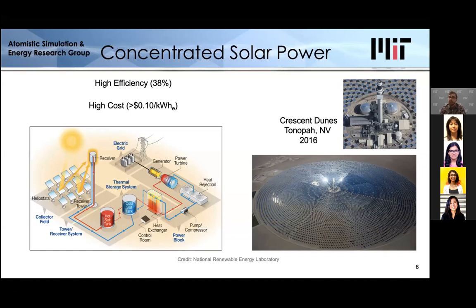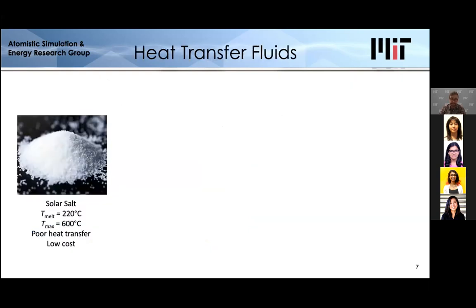So this high cost is an important component of this system. And there are avenues to reducing the cost, and this is what this first topic was about: let's consider all of the different components in the system, and see where cost reductions can be made. And a significant cost reduction can be made by increasing the efficiency of the heat to electricity conversion step. And the best way to do that is to increase the temperature to enable different types of converters. Unfortunately, the salts that are used for this application have a maximum operating temperature of around 600 degrees Celsius.